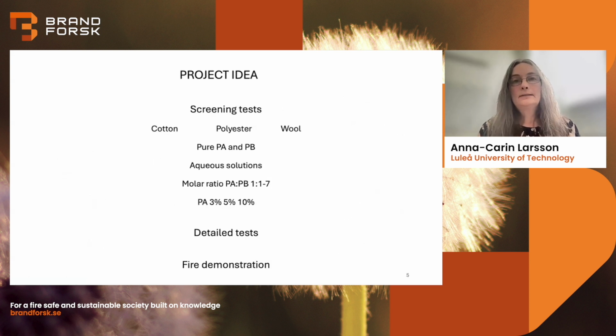We started with screening tests, choosing three different materials: cotton, polyester, and wool. We used pure phytic acid and pure purine bases, made aqueous solutions, and dipped our textiles in those solutions with varying molar ratios between phytic acid and the purine, and different concentrations of the PA. With this first screening we look at which compositions give the best properties, then continue with more detailed tests on those. In the end, we make a fire demonstration test to see if the small scale results also work at a bigger scale.